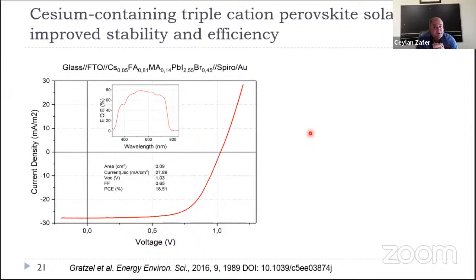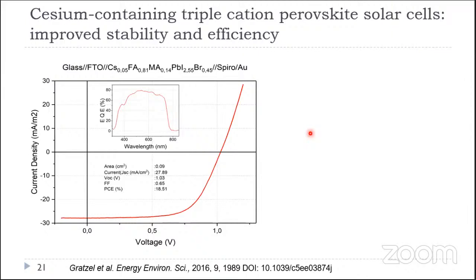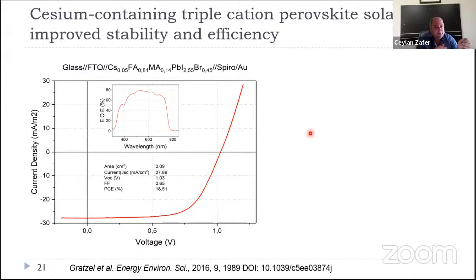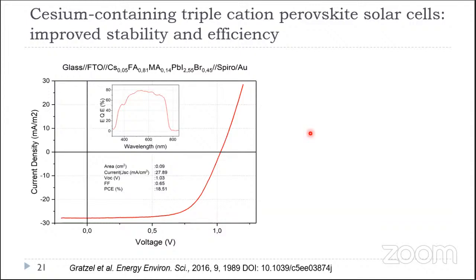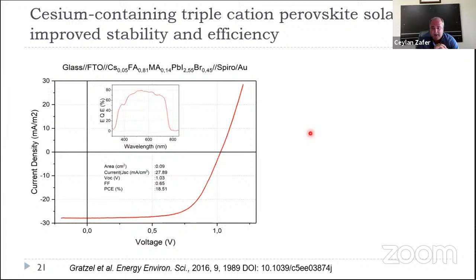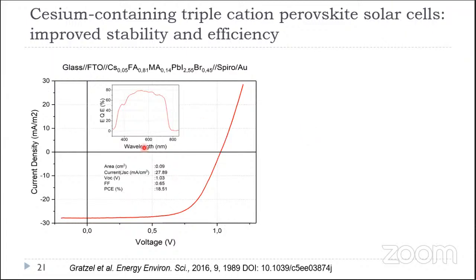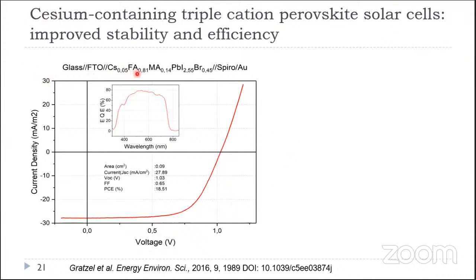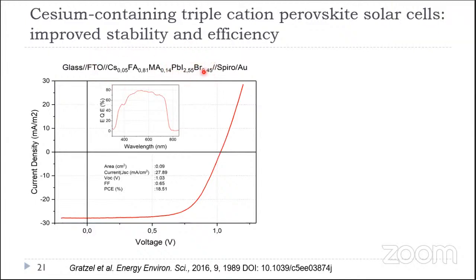And insertion of cesium and formamidinium into the methylammonium lead iodide perovskite improves drastically the performance and the crystal quality of the perovskite. And as seen here, this is work performed in our laboratories: cesium, formamidinium, methylammonium, lead, iodide, bromide. This is a triple cation and double anion perovskite. We got a really good efficiency and very nice performance with the perovskite solar cells. And is this enough for the performance improvement?